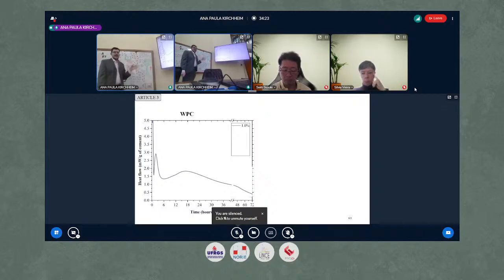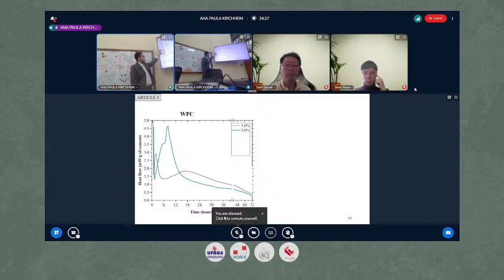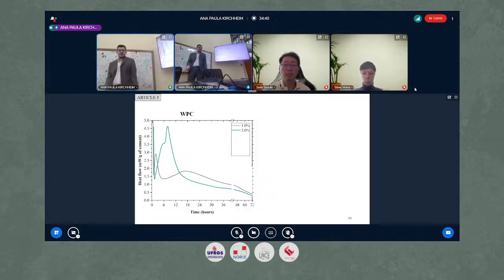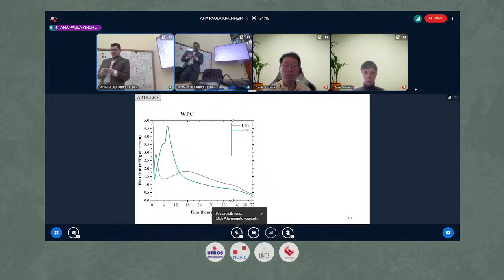Then we add more sulfate, and here they delay this peak until after the main silicate peak, and here we see the behavior that was expected. This peak occurs early. And here we observe the influence of the undersulfated mix on the C3A reaction. Then we have more, and we have the optimum zone.